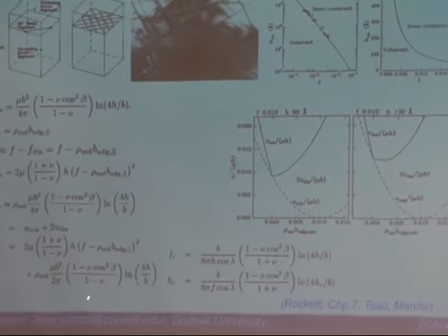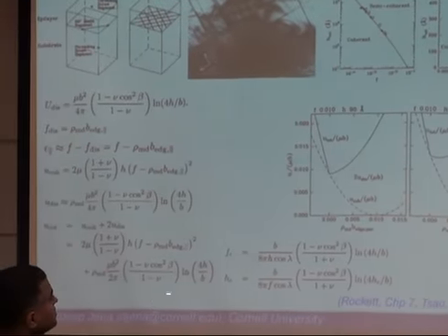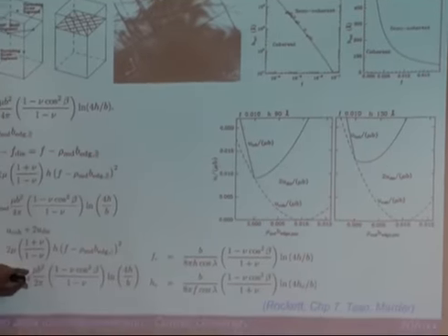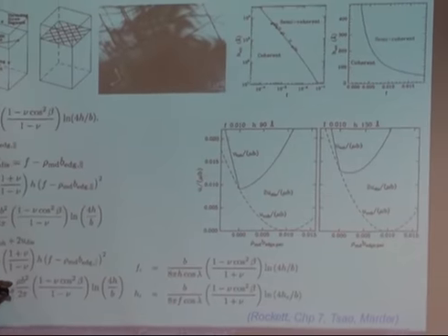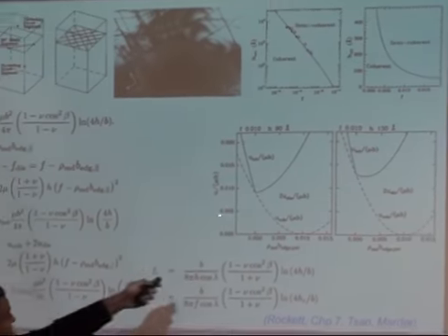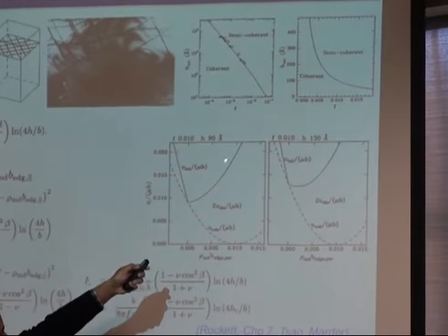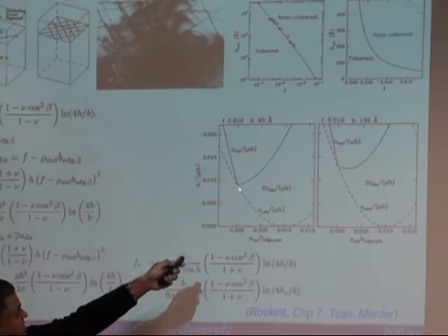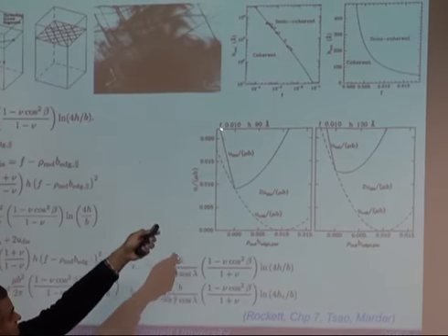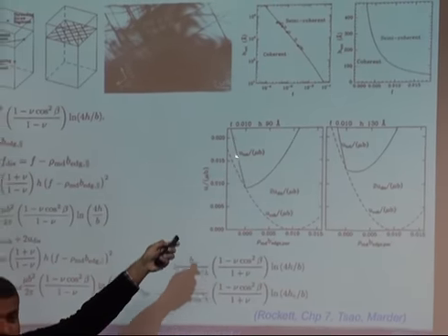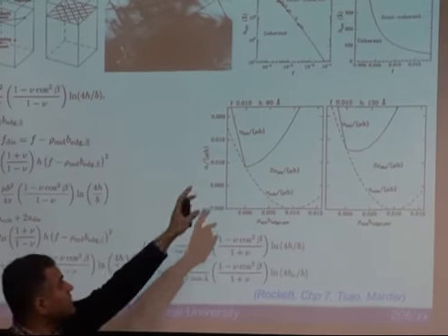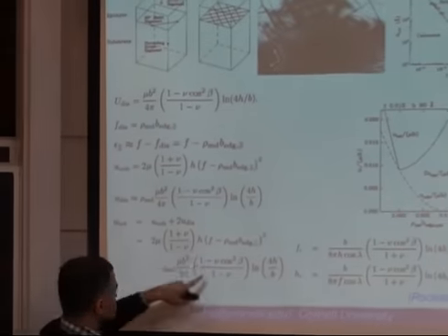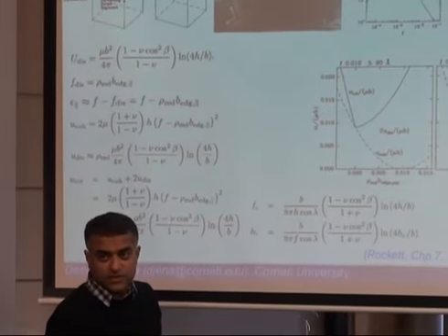Whereas the energy of dislocations, that term, it's very faint here, but that thing really just depends linearly on the density of dislocations. More is the density, more is the energy of that. It's a little hazy here, but it goes like that, right? And you sum the two, you sum the parabola with this. So obviously that 0 point remains here, but this is the total energy of the whole system now. Right? So this has been plotted at 90 angstrom, meaning the h is 9 nanometers. This h is 9 nanometers, right?